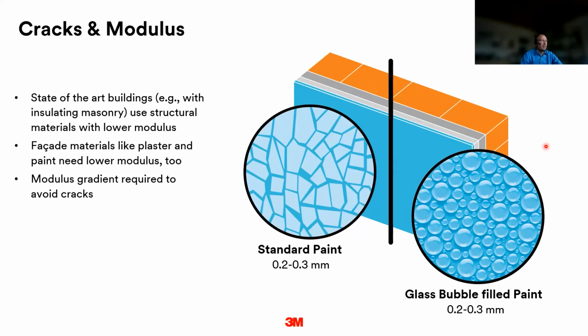new materials. We have the challenge that if we work, for instance, with insulating bricks, the masonry nowadays is not as stiff as it was in the past. So there is more movement, and therefore also the plaster, the stucco, and everything that is applied on the facade needs to have a lower modulus in order to prevent cracks. So if you don't decrease the modulus of these products on the facade, then you get a lot of stress in the paint, for instance, or also in a plaster, and you have a high crack susceptibility.